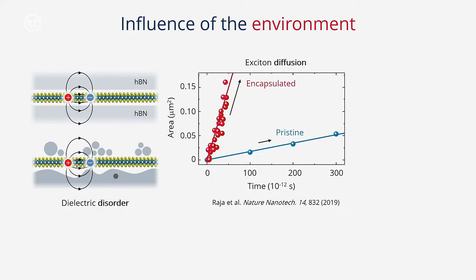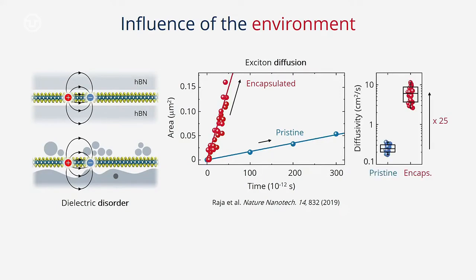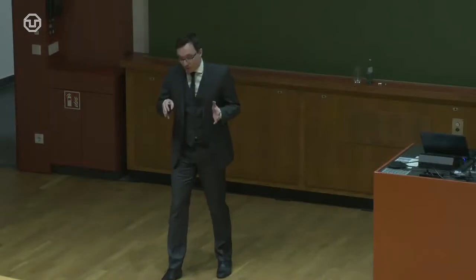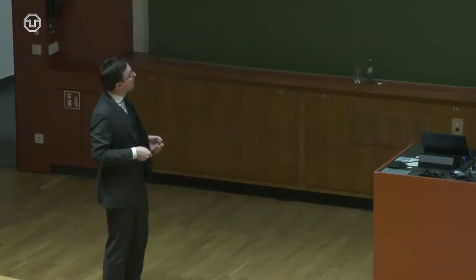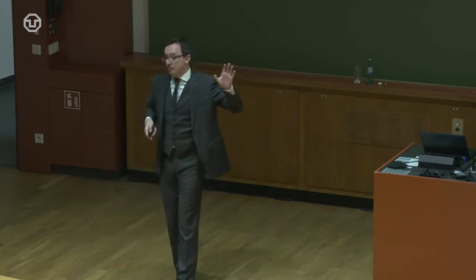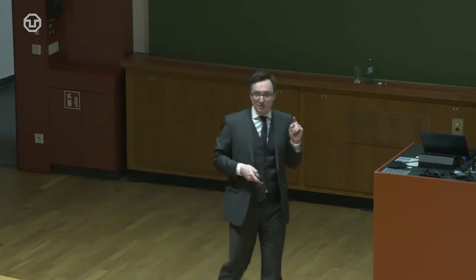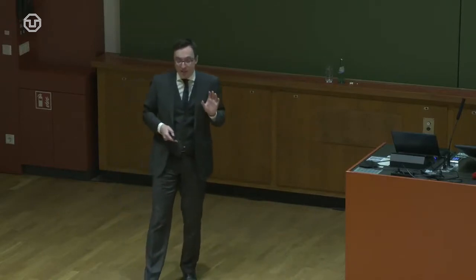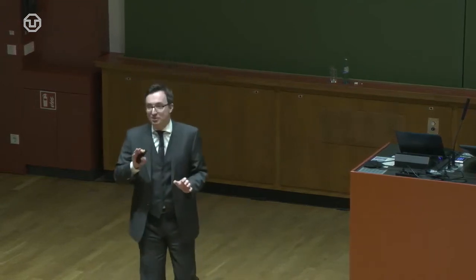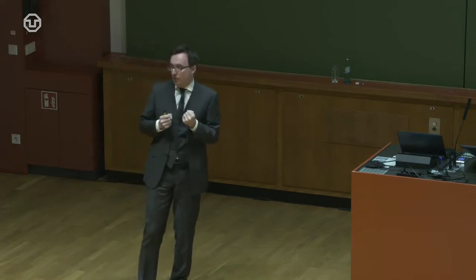And of course, we can do statistics, and we should do statistics. And there we see it's about a factor of 25 enhancement in mobility. So the result here is not only that the excitons can propagate very rapidly, and this is all room temperature. But for the experts in the audience, if we compare it with effective mobility of electrons, because those are usually the numbers people have in their mind when they think about mobility, it is something like 400. And for an excitonic system at room temperature, it is arguably one of the highest mobilities, and maybe, and this is always a very dangerous statement to make, maybe even the highest. This is always hard to tell. But it shows that this particle, despite being strongly bound and relatively small, can also be very mobile. And that was one of the first results that was very encouraging for us.